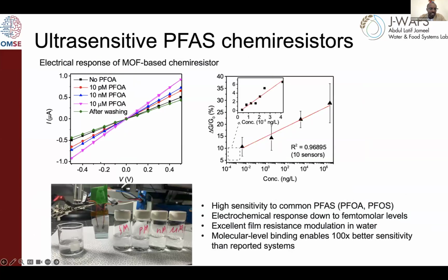So after figuring out how we can grow these materials into thin film, we're investigating the resistor response. Here I picked a couple of graphs. Maybe the one on the left shows the initial conductivity of the MOF. So the MOF gets doped by the presence of the PFAS. Here we're still figuring out how selective this is, or how it can distinguish between different PFAS. But as you can see, the current gets higher, almost more than double, as you increase the concentration of PFAS, in this case in a buffer solution.